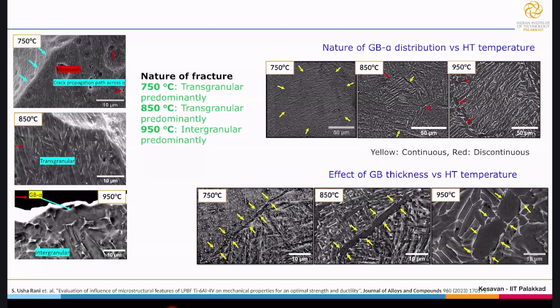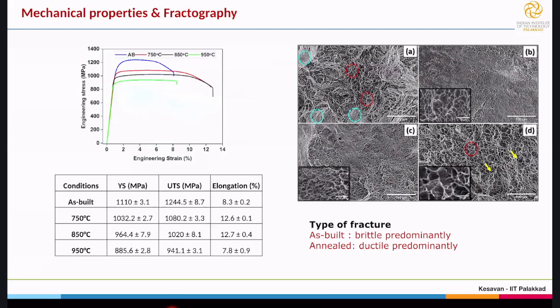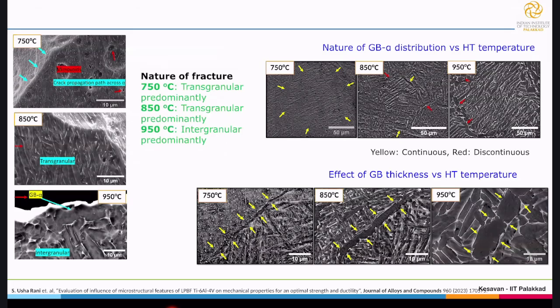You can see here, with increasing temperature, the amount of beta is increased. There is a clear distinction. But we cannot keep increasing the temperature. There is an optimum. You can see what happened if you increase the temperature further. At 950 degrees Celsius, the strength has decreased considerably, and the ductility also decreases, right? So there is an optimum value, between 750 and 850. Maybe this 850 is what we found as the optimum temperature for heat treatment.